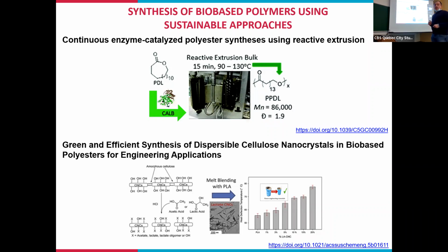In this case, the HDT, the heat deflection temperature, is strongly improved by adding a certain percentage of the nanocrystals. What it means is that you can use PLA for engineering applications, such as automotive parts, for instance.